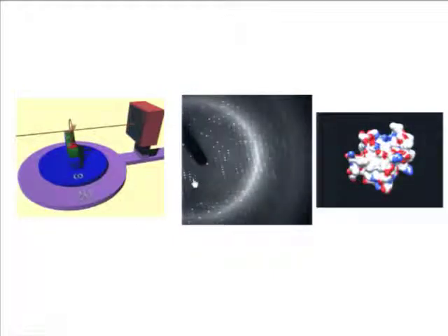So if we have a single crystal, we select the right diffractometer. This is a kappa geometry. We collect data upon rotation of the single crystal around different axes. We collect data which look like this, and I like this video very much because, as you will see, it shows how the reciprocal space cuts the Ewald sphere. So I use it a lot for teaching purposes. It's a very nice video. And if the data are complete and the resolution is sufficient, we get the structure.